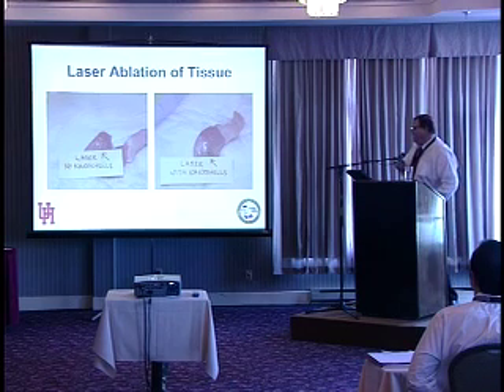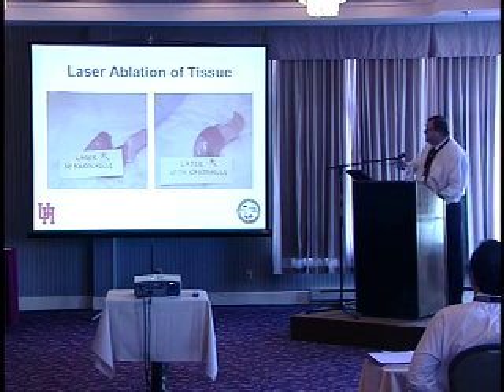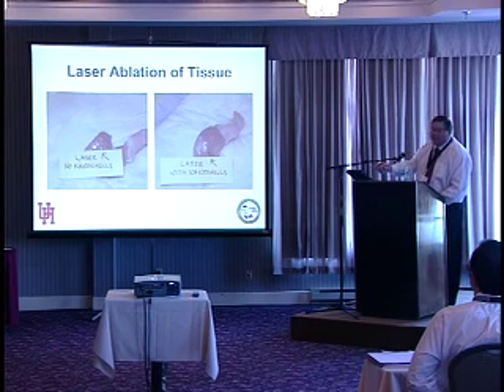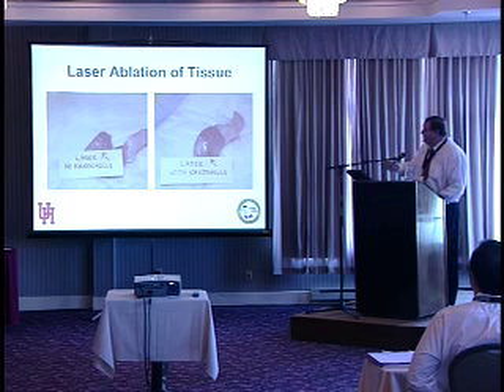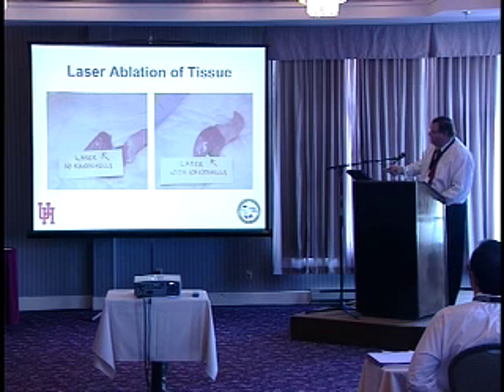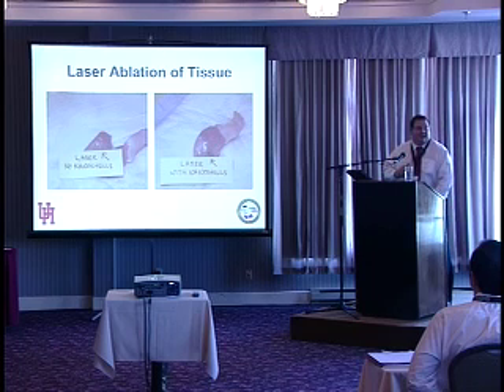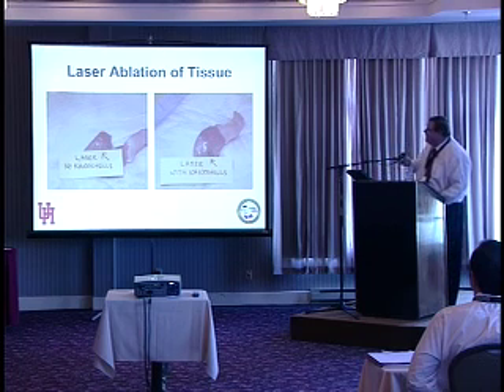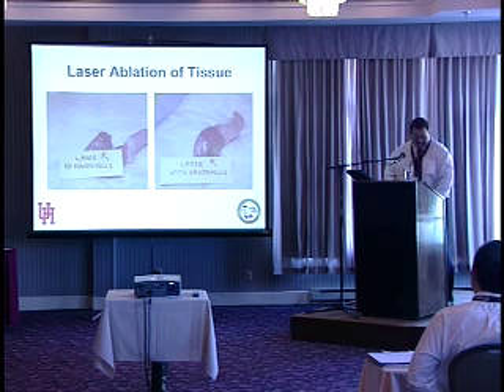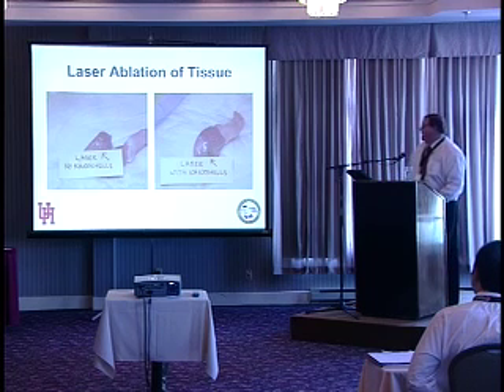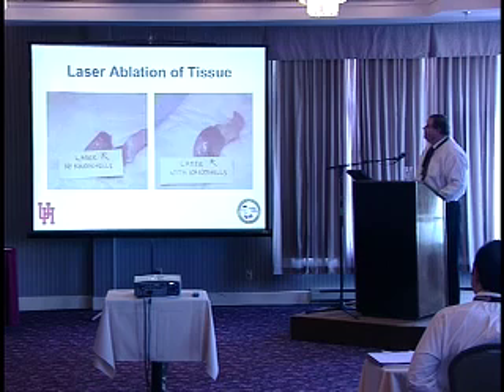There's a much simpler way of demonstrating the same concept. Here's a chicken leg. Take a chicken leg, blast it with a near-infrared laser, nothing happens. Okay, but if you inject nanoshells under the layer, you see you can burn a hole in the chicken leg using the laser. So I think this is a cheaper but perhaps more straightforward demonstration of that effect.